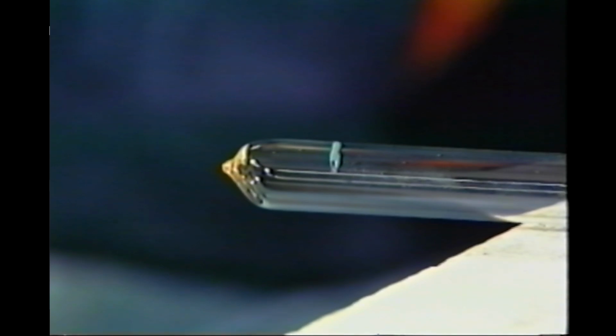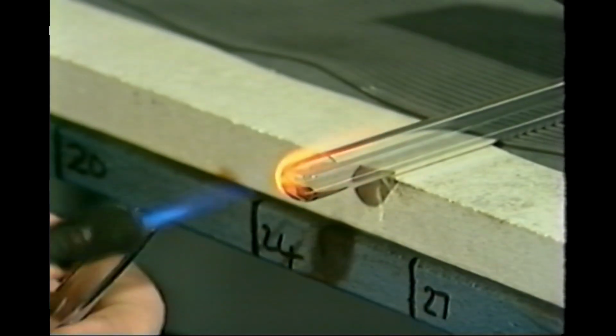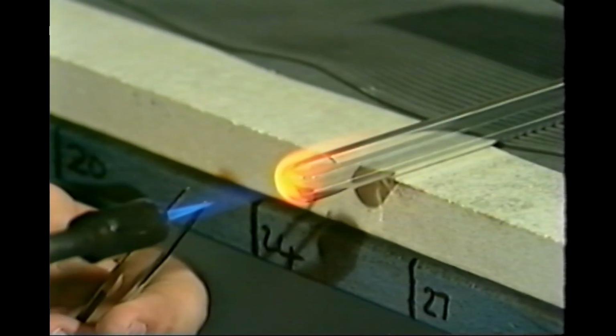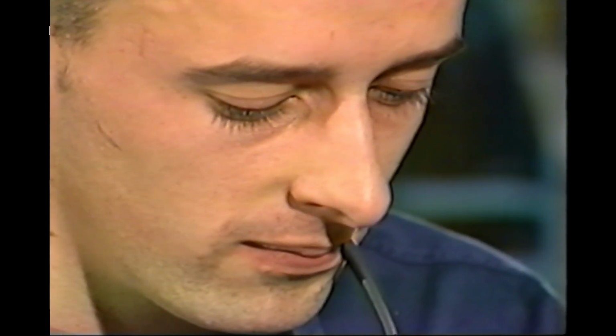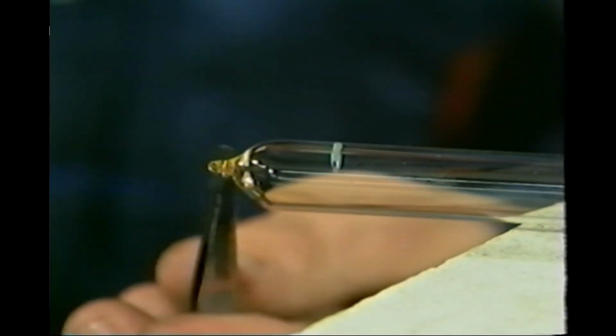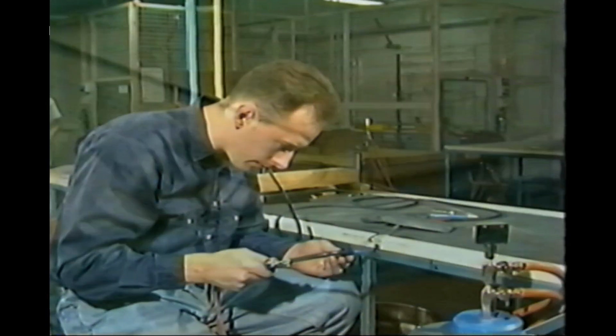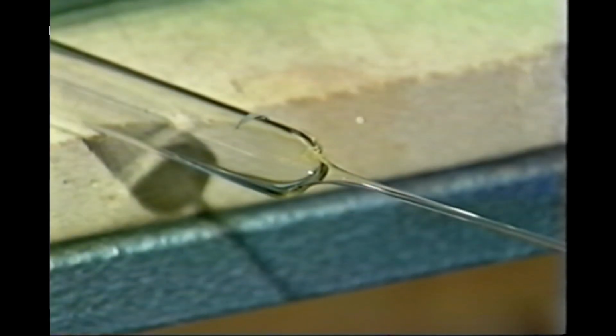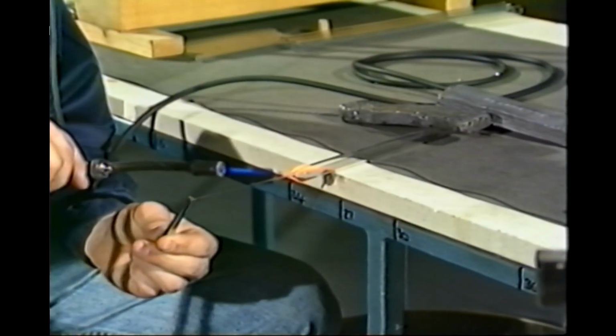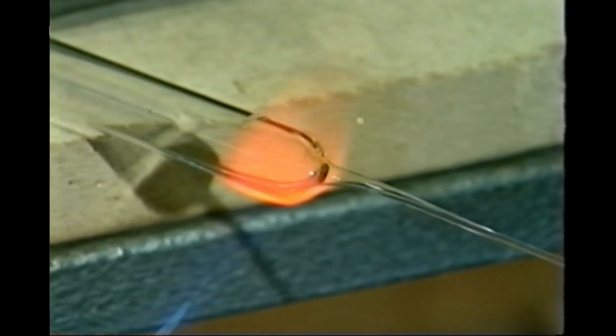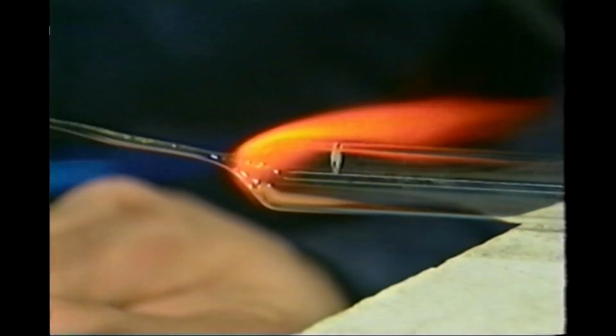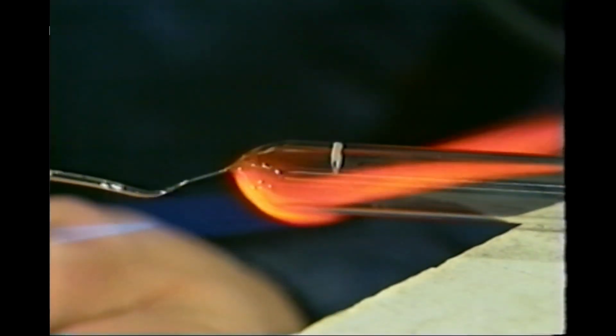Again, using the small flame, melt the closed end by pointing the flame directly at the closed end until glass is red hot. Remove the flame, blow gently into the tube via the blow tube. The hot end will bubble slightly. Grip this with the tweezers and pull outwards until the glass solidifies. Now melt on the shoulder of the closed end, rotating the flame at speed, and pull gently with the tweezers until the excess glass is removed.